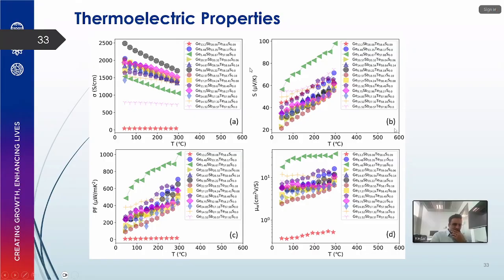For different ratios of germanium and antimony atomic percent, we measured the thermoelectric properties of 16 samples. We can see that a particular ratio of germanium, antimony and tellurium gives you a power factor close to 1 milliwatt. It's still 4 times lower than the bulk samples. I think that is due to grain size. Because the grain size is smaller here, we have a lower power factor, but that helps to decrease the thermal conductivity as well.